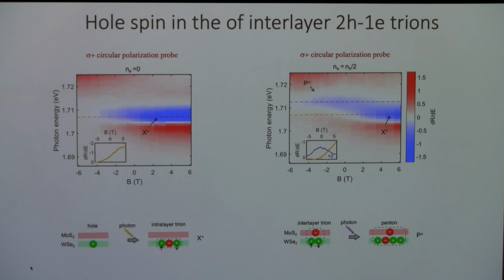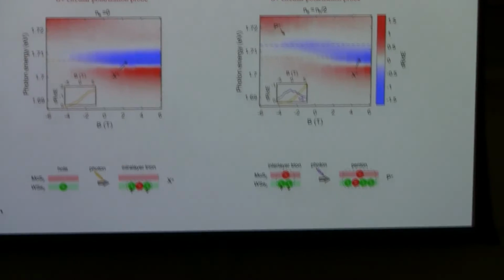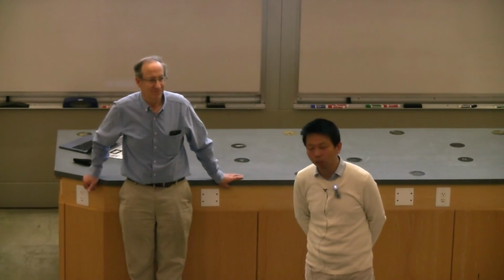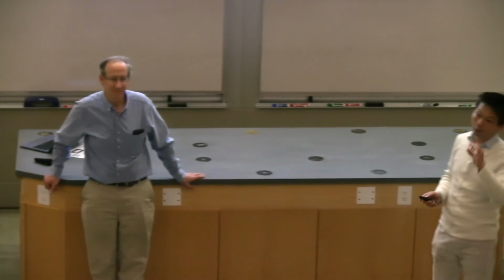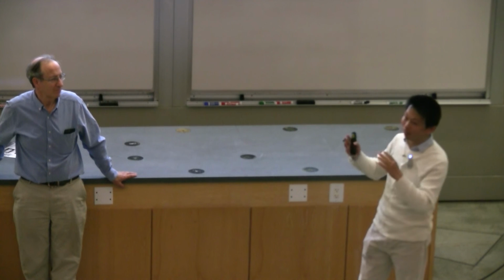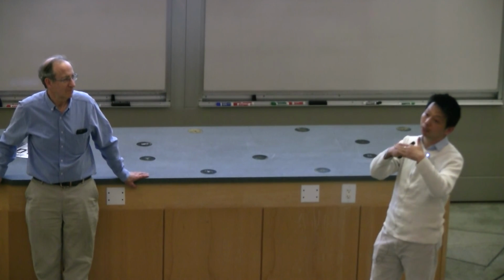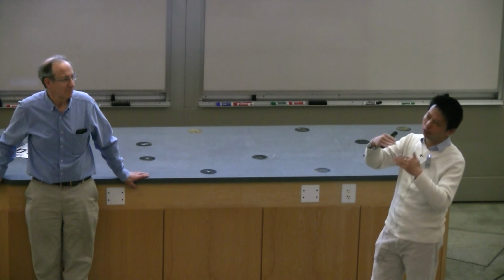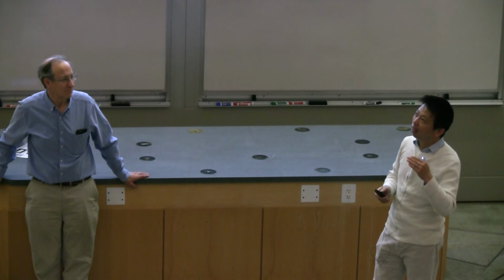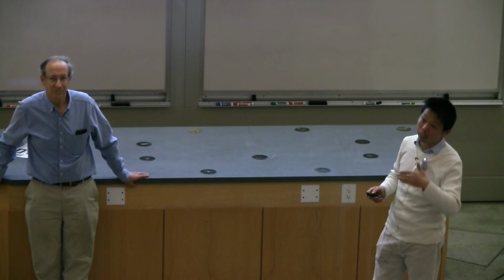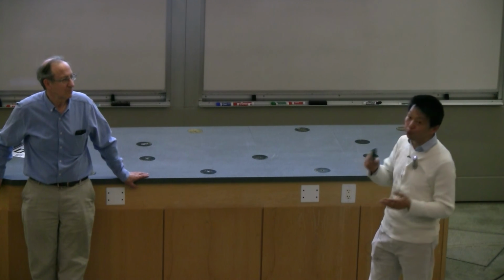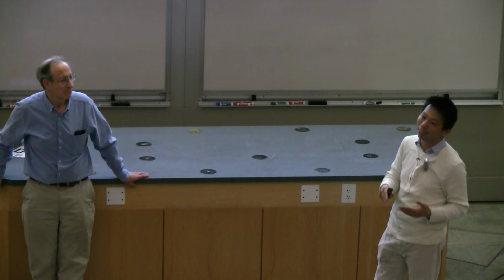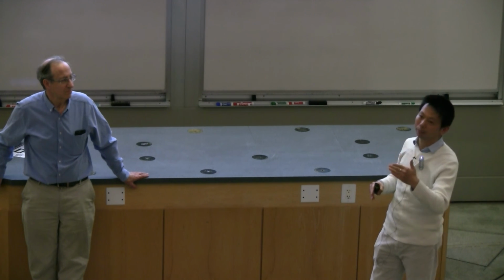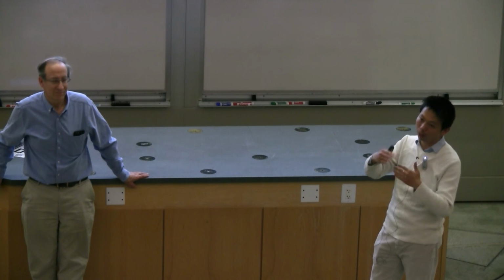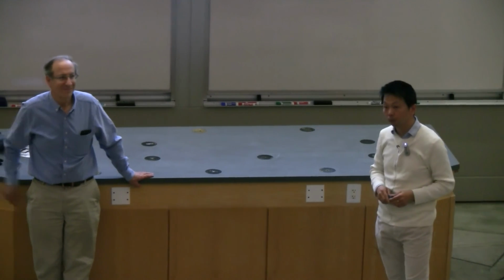Another question, yes please. Just an estimate maybe: what is the interlayer exciton lifetime in these systems? Interlayer exciton lifetime. Okay, it depends on the HBN thickness very strongly. For the part where we mostly study the excitons, we use 2 to 3 nanometer thick HBN. Based on the leak current, we estimate the lower bound of the lifetime is hundreds of milliseconds, so it's about 100 milliseconds to a second. If we push the HBN to be really thin, only say 2 layers, then the lifetime is more like 100 nanoseconds to microseconds. So it depends on the HBN thickness very sensitively.